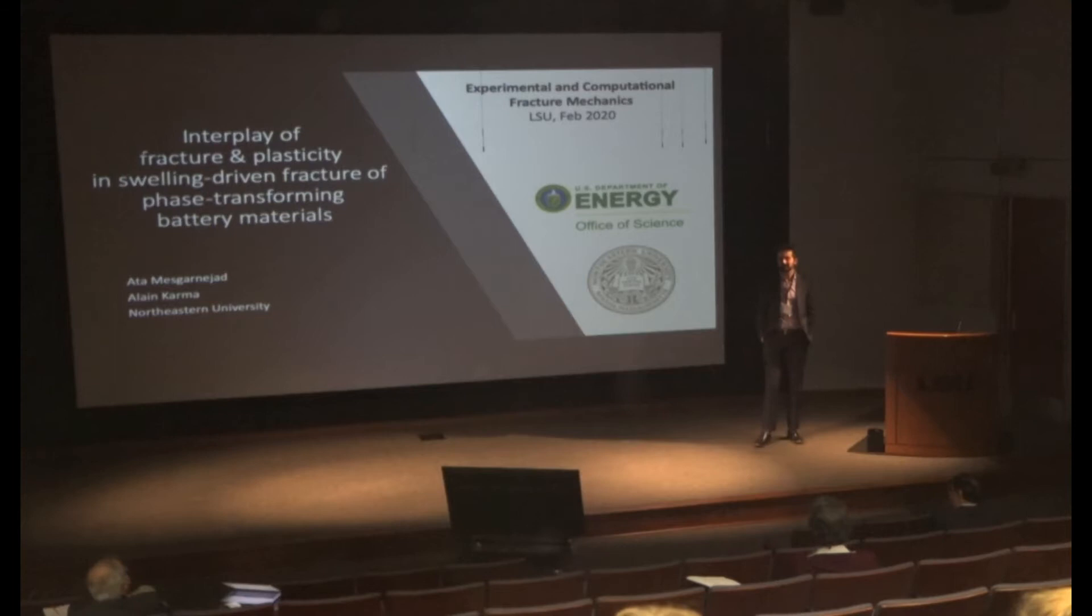Carbon only expands about 2% once you put lithium ions in it, but carbon's theoretical capacity is about 400 milliampere hours per gram, so it's very low. Electrochemists looked at the periodic table and asked what is under carbon—silicon and germanium—and the theoretical capacity is an order of magnitude larger.